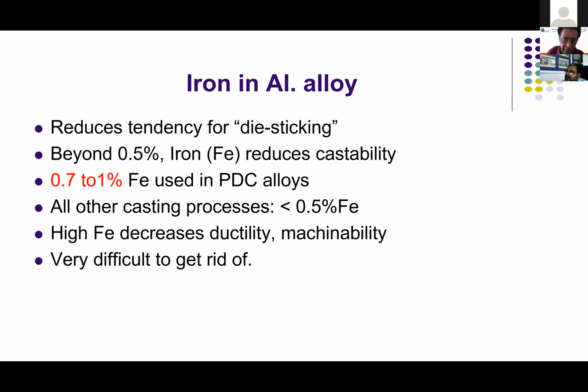Coming back to alloy, iron. Iron is not an alloying element per se. I repeat, iron is not an alloying element per se. Aluminium has got a high affinity to iron. Molten aluminium literally eats iron, whether it is a spoon or ladle or skimmers or dross removers, it just will dissolve in molten aluminium. So we have to take proper care while using steel spoons or steel skimmers. It should be properly coated with oxide so that the metallic surface does not come into contact with the molten metal.